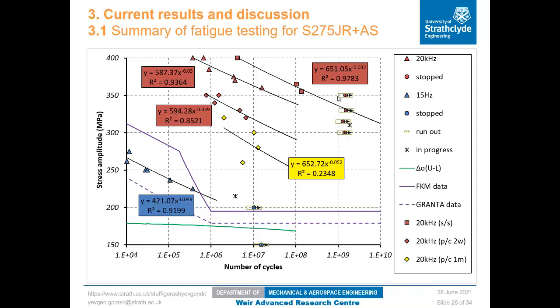So this value has been applied to the fatigue limit of 350, and it has predicted the fatigue limit at normal frequency at around 180 megapascals. That agrees quite well with the data provided from literature. So FKM fatigue data collection predicts the fatigue limit at roughly 190 megapascals, and the fatigue limit from the GRANTA data set is around 175 megapascals, which is quite a good prediction. And I should add that the actual fatigue limit found for this data set is around 200 megapascals.